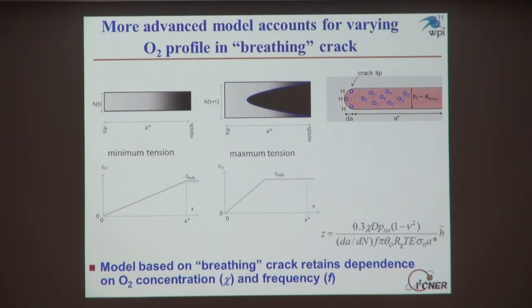But when the crack opens, we actually need to flow some gas into the crack to make sure that the pressure is equalizing inside the crack and outside the crack. And so what Reiner is showing here is that we might get gas flowing into the crack by laminar flow, and it originally has this type of profile, but then it quickly diffuses in the lateral direction. But what we'd ultimately wind up with is an oxygen distribution profile that looks like this.